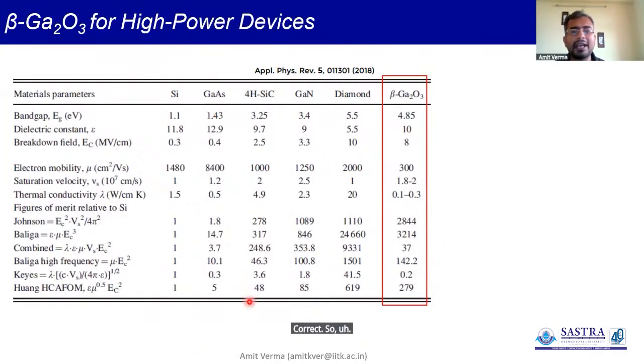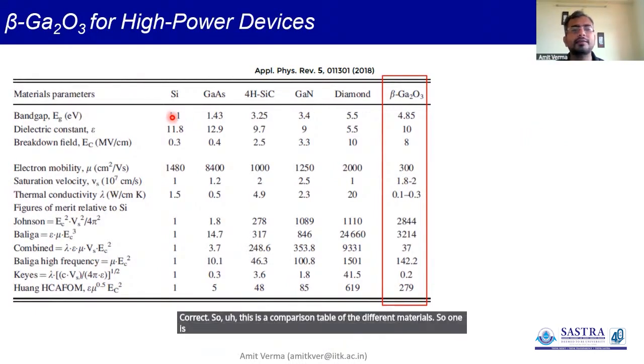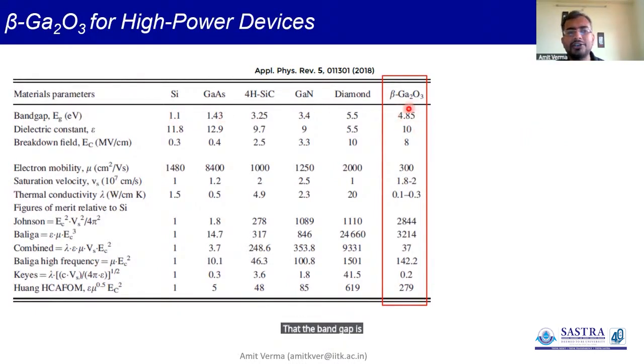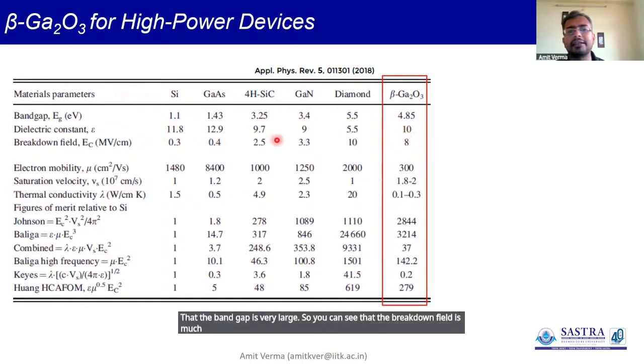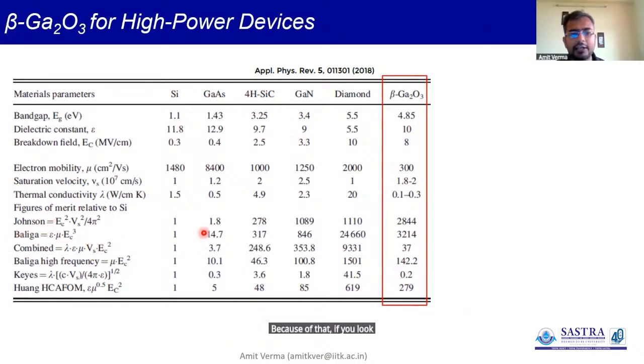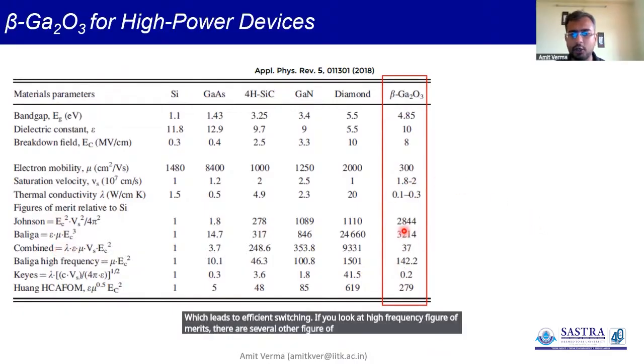So this is a comparison table of the different materials. One is, of course, obvious that the band gap is very large. So you can see that the breakdown field is much larger than silicon, gallium arsenide, silicon carbide, and GaN. Because of that, if you look at Baliga's figure of merit, it's much higher, which leads to efficient switching. If you look at high frequency figure of merits, there are several other figure of merits. There also, it's quite good.